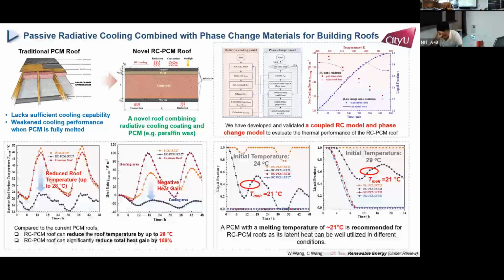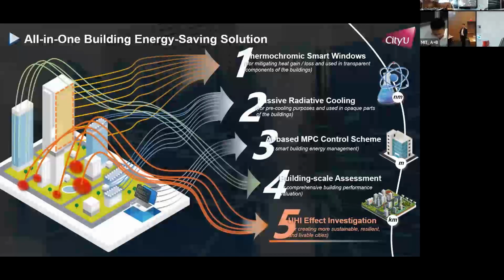validated by experiment, and we found that with this novel radiative cooling PCM roof, we can reduce the temperature by 28 degrees Celsius and reduce the total heat gain by about 170%. And the best melting temperature of the phase changing material should be optimized at about 21 degrees Celsius in Hong Kong's climate.